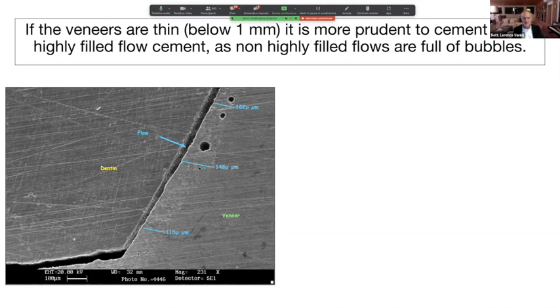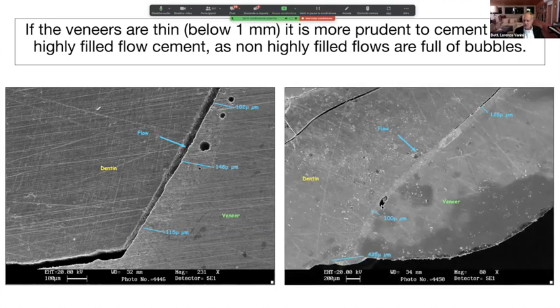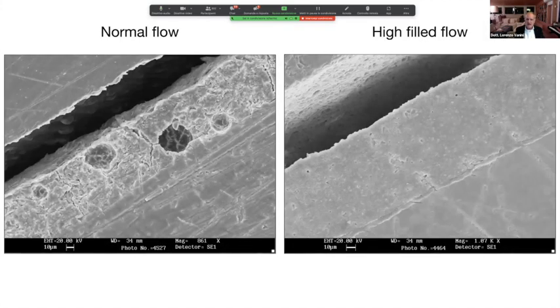We did a lot of tests, and you see that this flowable cement is full of bubbles, and the bubbles create problems because bubbles contain oxygen, and oxygen inhibits the polymerization. From the bubble starts the internal microcrack, and this reduces the strength and the resistance of the bonding phase. Look, bubbles also here. These are laminates bonded with a normal flowable cement, while if you use a high-filled flowable cement, you don't have these bubbles. This situation is much better than that one.